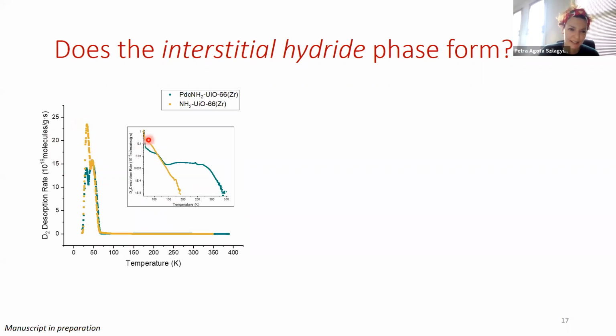Secondly, there is a little difference here as well. Still, the empty framework results in the desorption of more hydrogen at around 80K. And we had previously assigned this desorption peak to desorption from the amino groups. And once again, because of the presence of the palladium particles, the amino groups are not quite as accessible for the hydrogen as in the empty framework. But perhaps the biggest difference is here. You can see that above 200 Kelvin, no desorption event occurs from the empty framework. So we can assign this desorption to that from palladium. So this will be chemisorption from palladium.